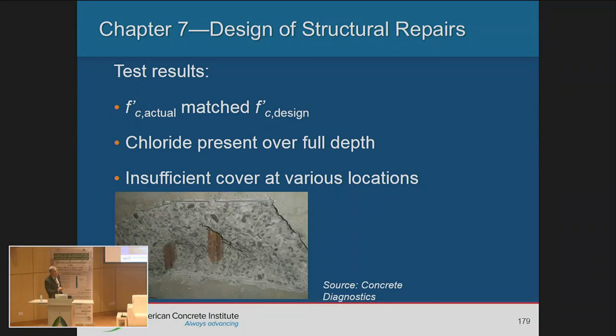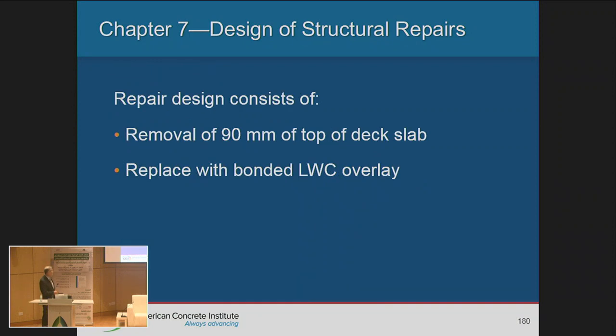Well, the actual concrete strength matched the design, so that's fine. So we're using the 25.9 or 26. The chloride was found to be over the full depth, and in some cases they found that the cover was not sufficient. For example, they required 25 millimeters, and it was less than that. So it did not satisfy the code requirements of that time. So the engineer's solution was to remove about 90 millimeters of the top of the slab, which is about half the slab thickness. So they took about half the slab thickness away, and they wanted to replace it with bonded lightweight concrete.